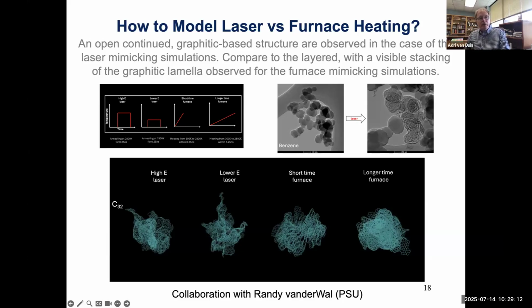We use the same material. We use here C32 as a growth, so a larger scale polyaromatic hydrocarbon. And we can expose them to high intensity lasers, low intensity lasers, short-term furnace and longer-term furnace. And you can very clearly see how that affects the carbon structure. So we're now also using all sorts of machine learning tools to really distinguish the morphology. But you can see that we get a much more open lamella type structure compared to a much higher density, compact graphitic structure.